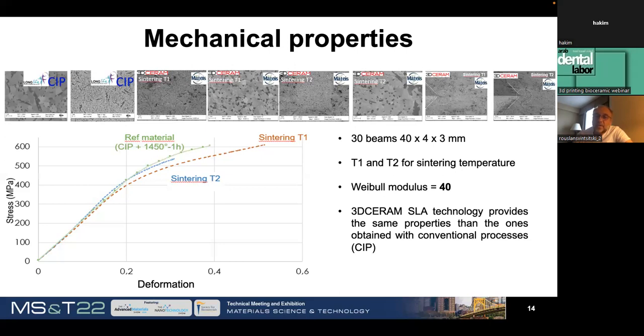Of course, this is a simplified diagram because we did many more tests, not just temperature T1 or T2 was tested, but also soaking time, different ambience, environment, etc. But here I just give you the results of the study where we found the sintering temperature T2, which is roughly similar to the reference material conventionally manufactured by cold isostatic pressure. It was implemented on beams of 40 by 4 by 3 millimeter dimension, and we could obtain a Weibull modulus of 40, which is very nice for the mechanical properties of ceramics.